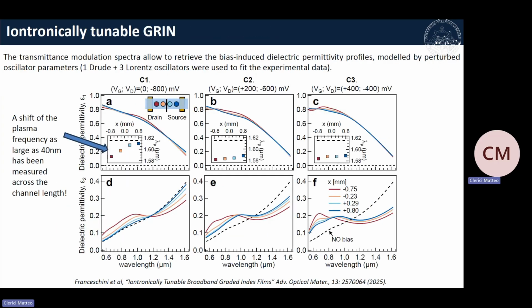When you convert that and extract the electric permittivity, real and imaginary part, you see that pretty much what changes is the plasma frequency of the device, because the PEDOT can be modeled with a Drude oscillator and a set of Lorentzian oscillators, but actually the main change that we found was on the Drude part. So we are modulating the plasma frequency about 40 nanometers along the channel.